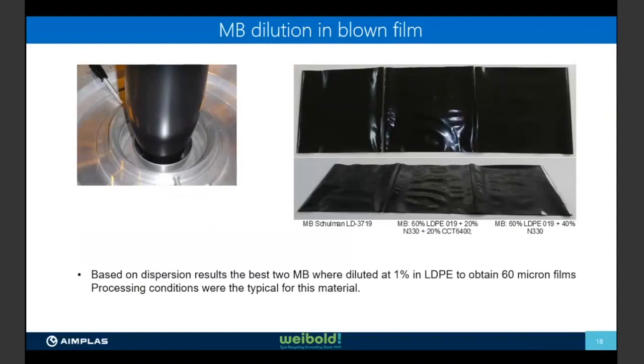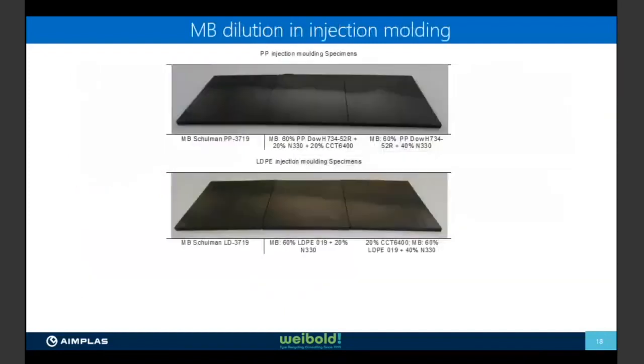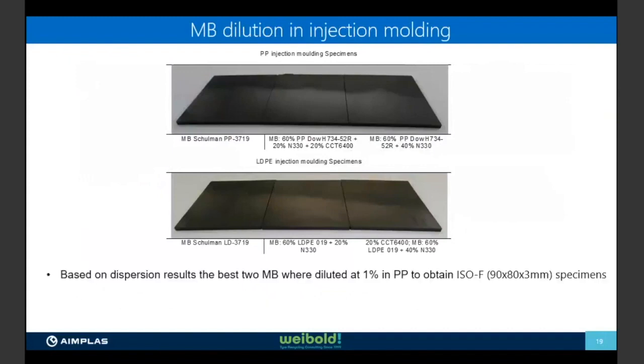And okay, as I mentioned, processing conditions were the typical ones, not to go too much into detail. And no significant differences were detected between recycled carbon black and conventional carbon black master batch dilution. So if they work properly, we did the same with injection molding. We obtained different specimens. In this case, we obtained these plaques by injection molding. Big specimens just to see if we can find difference in the surface and so on. As you can see, it's quite complicated to find a difference between any of them. So it means that the dispersion has been very good in all of them, and the processing was good, no problems, no difference in processing. So they behave in the same way.